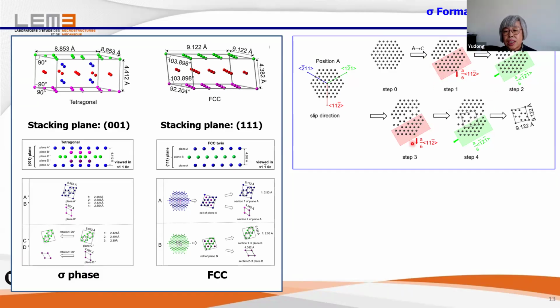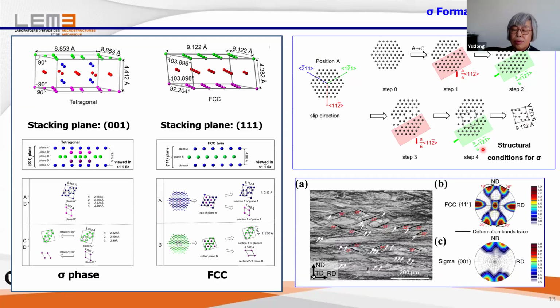Then we repeat these two processes here, and we can outline a motif. You see this motif here is exactly this motif. That means the transformation from FCC to tetragonal is made by the activity of the stacking faults. This also allows us to explain why these two planes are copied, because in this area we have a high density of stacking faults. So you see, without any in situ atomic scale characterization technique, we can resolve such an atomic pathway for phase transformation.